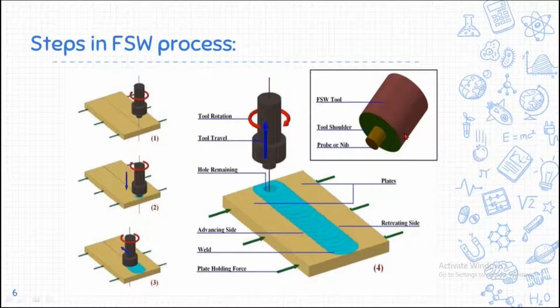Coming to the tool of the friction stir welding process. Here, if you see, this is the friction stir welding tool. The brown colored portion is the tool shoulder diameter. We plunge the tool on the plates until the tool shoulder touches the plates. And this is the tool pin or tool probe. This tool pin helps the welding process to mix the plasticized material. Mixing is the main objective of this tool pin, whereas the main objective of the tool shoulder is to create sufficient temperature to weld these plates.